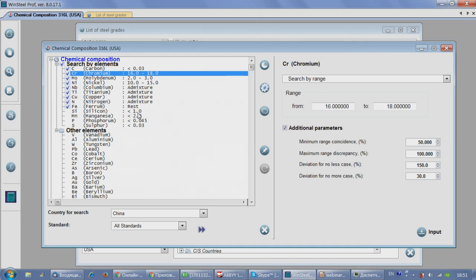For silicon, if we select it in the search, it will be by default from 0.3 to 1%. For manganese, it will be from 0.6 to 2%. And you can change this coefficient also. This one, deviation for no less case. In some compositions, for example, for some heat resistance alloys, we can find in composition nickel more than, for example, 68%. It is understandable that this is base element, and more than 68%, the maximum value will be 100%. It is easy to clear.